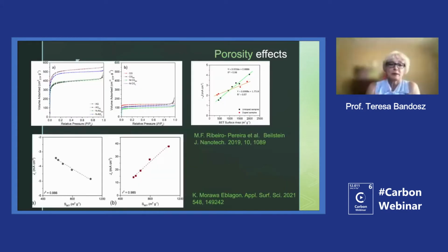But some results went a little bit deeper, like for instance the group from the University of Porto. They studied porous carbons and non-porous carbon, modified with nitrogen and non-modified. And indeed, they found a linear dependence of the kinetic current on the BET surface area. And what was interesting is that there were two different slopes of that dependence for non-modified carbons and for modified carbons. And it looks like the effect for non-modified carbon was stronger.